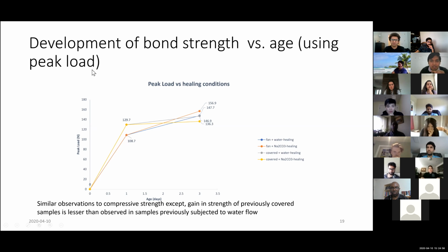And this is the same test. So this is the bond strength versus age. Again, the same kind of graph. After 1 day, I observe the two. So this is the covered specimens, and this is the fan specimens. And among these two, there is a difference. So there is a damage in terms of peak load. And after that, I leave them to cure under different substances. And then there is a similar observation in terms of sodium carbonate performing better, but gain in strength is less as compared to samples subjected to water flow.